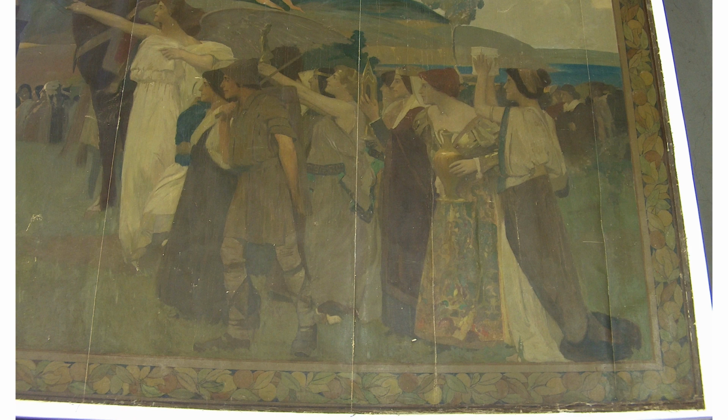There were also very interesting, someone at some point had taken duct tape and adhered it to the front of the mural. And the duct tape had long since gotten old and had fallen away, but the adhesive was left. And it was no longer sticky, it had chemically cross-linked, so that it was as hard as a rock. And again, here's the deformations from having been rolled.